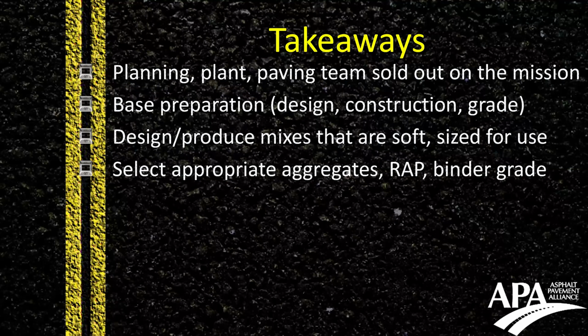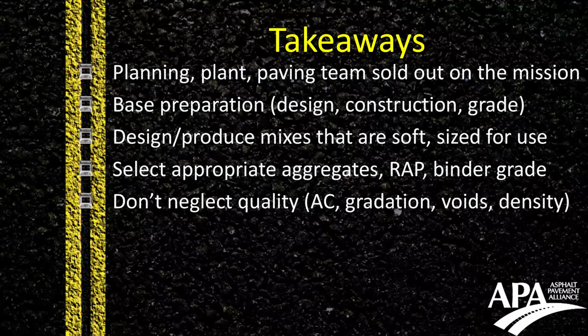You can imagine if you've got just a handful of trucks out there, and you're doing this work over the course of the day, and you've got a mix that's got too much RAP in it, or the wrong kind of binder grade in it, you could lose workability very quickly and not be able to get this material down and get it compacted the way that it needs to be. Don't neglect quality, and that goes beyond just the grade control. The mix needs to be healthy: the right kind of binder content, the right gradation, the right voids, and you have to compact it.